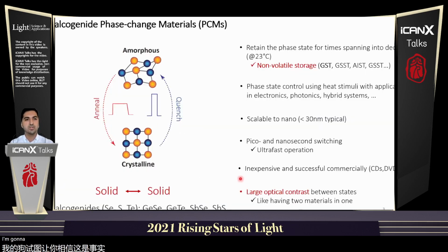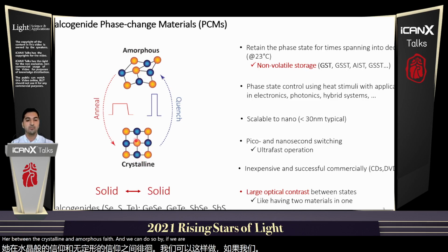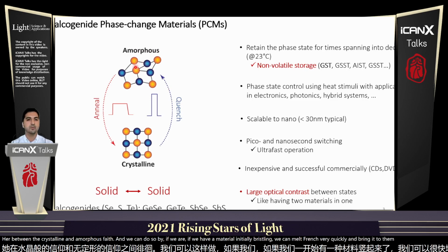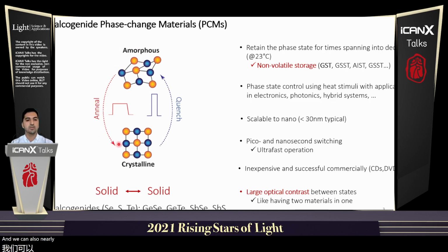So I'm going to introduce what I mean by phase change materials. I'm talking about chalcogenide alloys that contain one of the chalcogen elements: selenium, sulfur, or tellurium. And these alloys undergo a solid-to-solid transition between the crystalline and amorphous state. If we have a material initially in crystalline, we can melt and quench it very quickly and bring it to the amorphous. And we can also anneal over the crystallization temperature and bring the material back to the crystalline state.